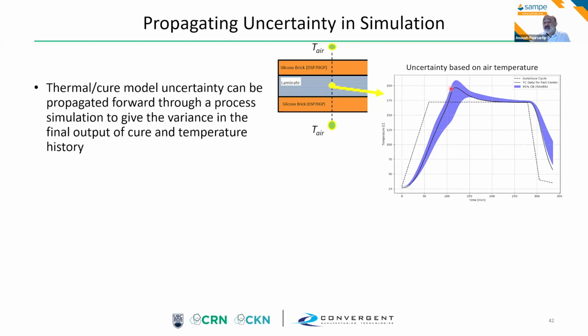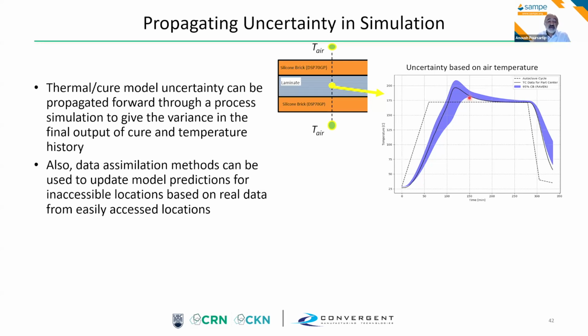So you could get a prediction that if you actually quantify the uncertainty would say you can have a huge exotherm, which is totally unacceptable, or you could have an exotherm that is acceptable. So then you ask yourself, where do I go from here? And the answer is, I can now get into data assimilation. What I can do is say, but what if I have other information, not a thermocouple in the laminate, because I'm trying to avoid that.